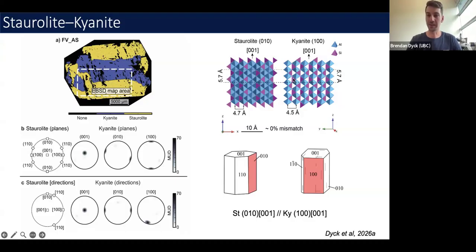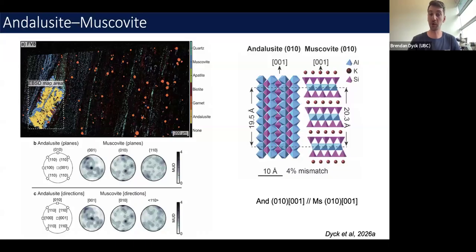We can see there's very little mismatch or coincidence between the spacing of, for example, aluminum to aluminum, or silica to silica in the staurolite and the kyanite. So there could be a lot of bond interaction across that boundary, and that could result in a very low energy orientation relationship. That's a simple one. Let's move into something that's a little bit more complex.